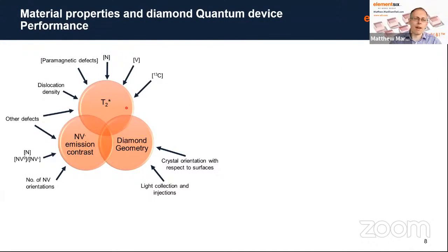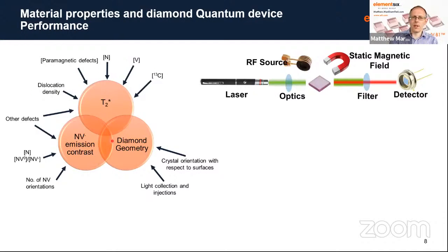Which is basically what I have here. The three main properties that we're interested in are the spin lifetime, T2 star, or for some applications it might be T2. The diamond geometry and how this affects the performance is obviously its ability to get the light out of the diamond, because you're measuring this red light. Any red light you don't detect obviously is wasted signal, so that's an important consideration. And NV minus emission contrast. So that's basically the emission you're getting from your NV minus defect that you're using. That's an important factor when it comes to improving the performance of devices.